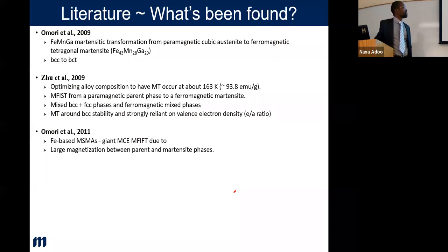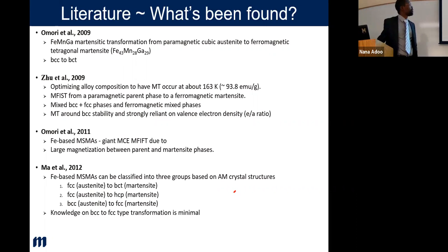In 2011, this forward magnetic field induced phase transformation was also realized by Omori again. And this was actually when the phases were being transformed from the FCC to the BCC and then back to a BCT. This is what he got. And then Ma et al., who worked on iron-based manganese alloys, also found these systems going on. It's either from FCC to a BCT, FCC to an HCP, or BCC to an FCC.